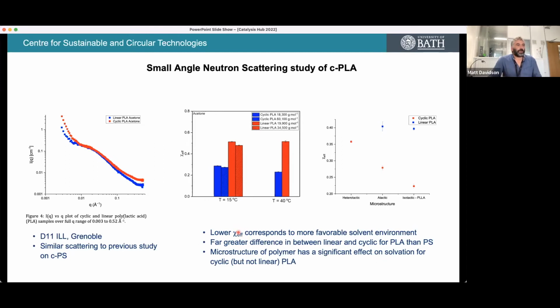First of all, if we look at this parameter here, the lower this is, it corresponds to a more favorable solvent environment. And you can see there's a significant difference here between the cyclic PLA in blue and the linear PLA in red. For the different molecular weights, there really isn't much difference, but there's certainly a difference between the cyclic and linear. And we can ignore the difference here, although there are some subtle differences in temperature. But if we just focus on this bit here, what we're saying is that the solvent environment in cyclic PLA is significantly more favorable than the solvent environment, this is in acetone, by the way, for linear PLA. A similar thing was seen for the polystyrene, but it wasn't nearly so differentiated between the cyclic and linear.